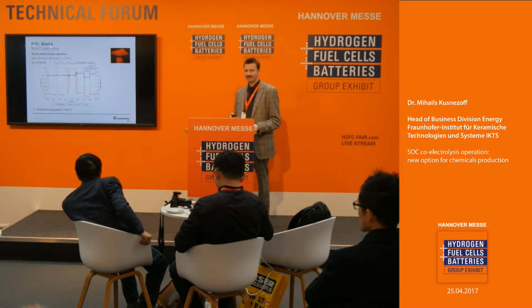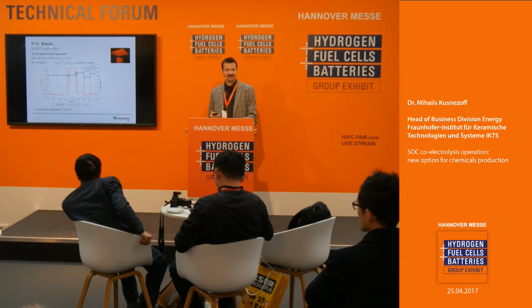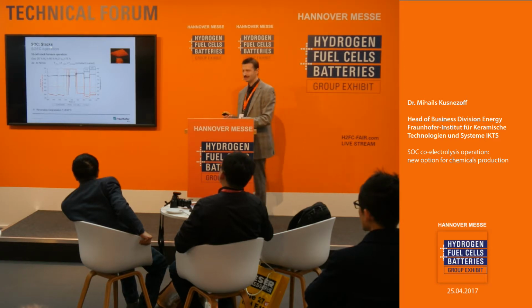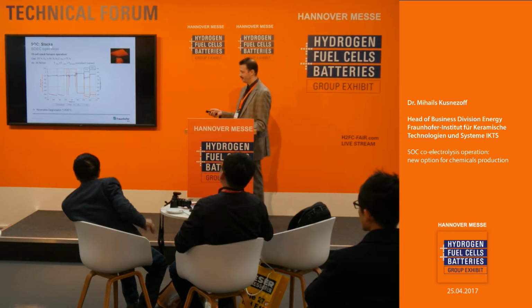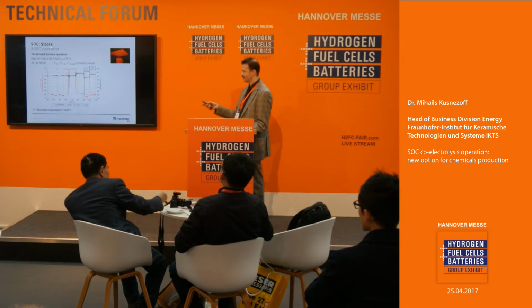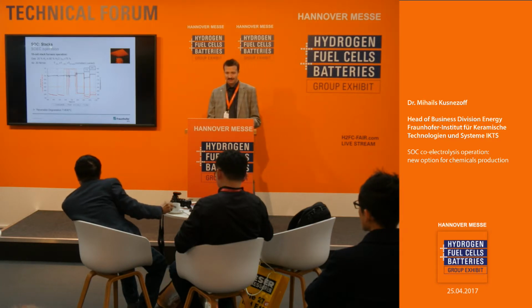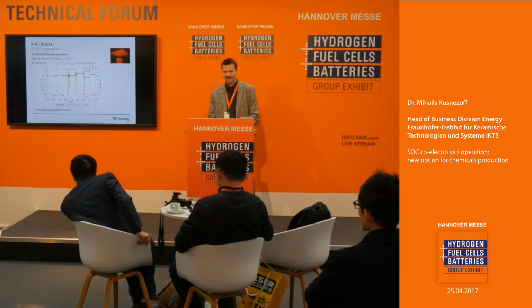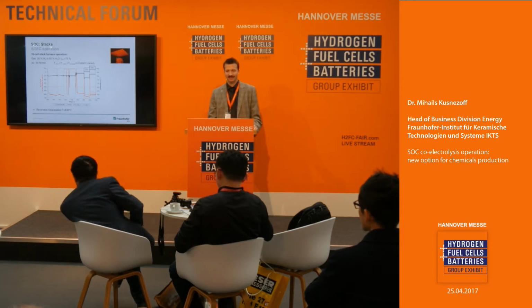We also observe in the stack operation the same effects we have seen on the cell level. So especially at 800 degrees C, we see some effects which are explained as a stabilization, which are also reversible. And if we increase the operating temperature, then they are diminishing.